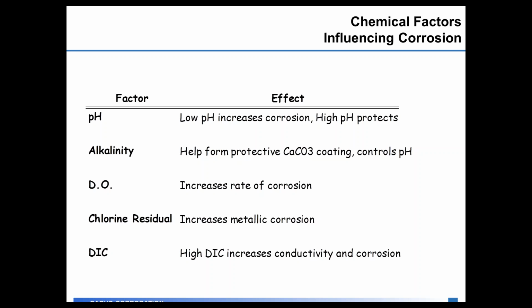You can have dissolved oxygen in the water, which increases the rate of corrosion. This will typically show up if you pull a sample of water at the consumer's tap and the water looks milky white for the first few minutes, but then as the bubbles dissipate, you no longer see the milky white, you have clear water. It's a hallmark that you have high dissolved oxygen in the water.